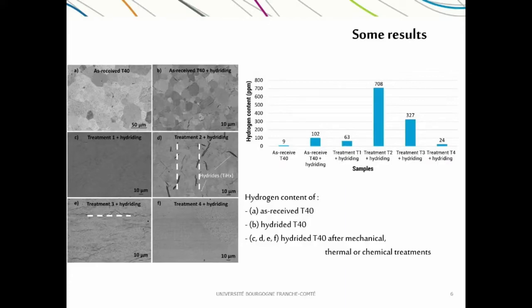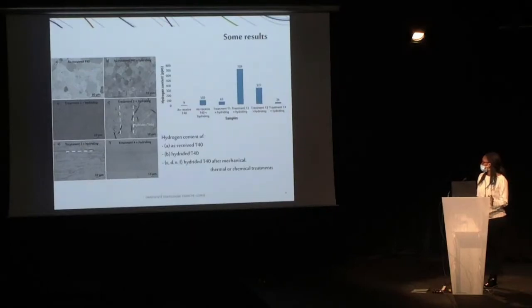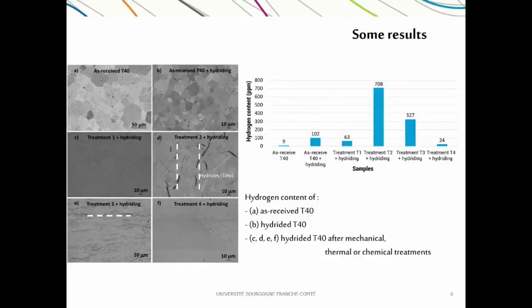Also, we can see that the more hydrogen decreases in the material, the less there is precipitation of hydride in the material, as you can see on figures C and F, which correspond to treatment 1 and treatment 4 respectively. In addition, we can see that some treatments, such as treatment 2 and treatment 3, give a specific orientation to hydrides.